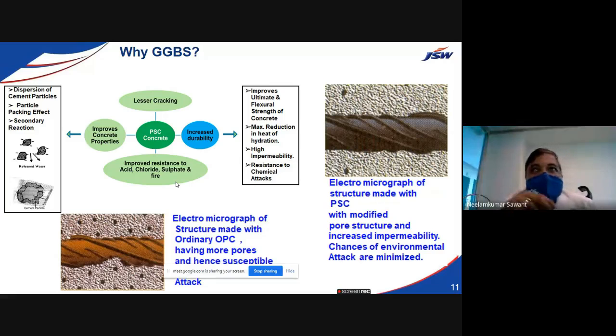Whenever rusting is there, it is an electrochemical process, and this bar will exert tensile forces on the concrete cover also. And we know concrete is best in compressive strength but weak in tension. So definitely spalling of the concrete on the surface and cover area will occur, the rusting will become much more, and the load carrying capacity of the structural member will be reduced. And if, instead of OPC, some content is replaced by GGBS, this porosity will be reduced, and your RCC bar will remain intact. So resistance to chemical attacks will be there, and this is a very good advantage of GGBS.